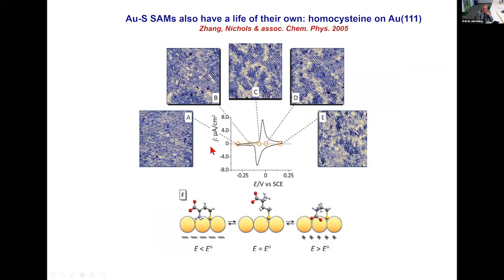We also have to realize that the functionalized alkane thiols, in this case homocysteine, with one carbon link longer than the cysteine itself, can also have an electrochemical life of their own. For example, homocysteine displays a very sharp voltammetric peak in the middle of nowhere, so to speak. There shouldn't be a Faraday process at this potential. And we know now this is a capacitor peak again.